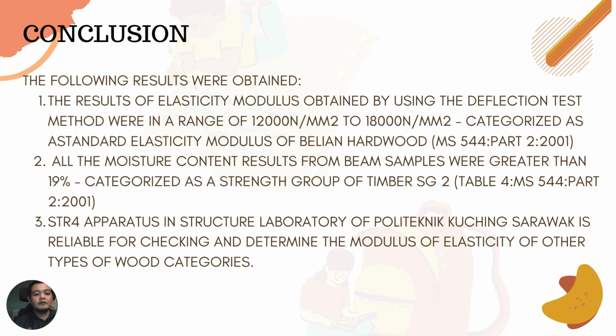For the conclusion, the study aimed to evaluate the mechanical properties of elasticity modulus of local hardwood timber, which is Belian hardwood. The following results were obtained. Number 1, the result of Young modulus obtained by using the deflection test method was in the range of 12,000 to 18,000 Newton per millimeter square, where these values are categorized as the standard elasticity modulus of Belian hardwood published in Malaysia Standard with Code of Practice Part 2 2001.